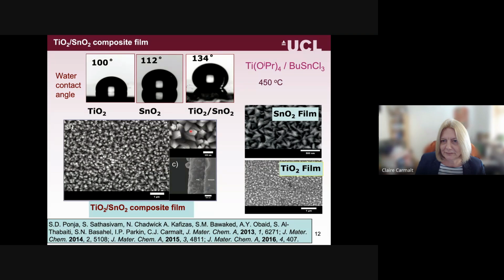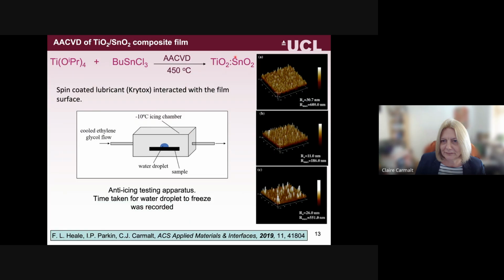Now they're of interest because they're not superhydrophobic, instead they're slippery. So rather than just being repellent to water, because they're slippery, they can also repel other liquids like oils and so on. But typically what you have to do is add a lubricant on top of your surface. And so that's what we did in the next step. So we made our AACVD film of our TiO2-SnO2, and then we spin coated a lubricant on top. And then we looked at them for a range of applications, such as anti-icing, anti-fogging. So essentially we just looked at how long the water droplet took to freeze, using this little homemade icing chamber shown here. These are just the AFMs of the films, showing you how textured the morphology is.